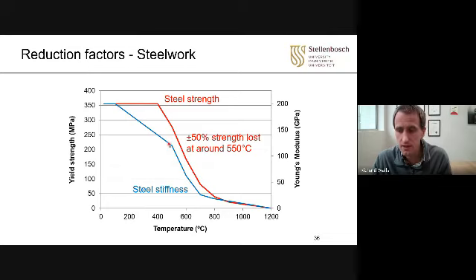So let's start thinking about steel and how steel is affected in fire. So this is the strength with temperature, the red line. As it heats up to about 400 degrees Celsius, the strength doesn't drop, more or less. And then at 400, it quickly plummets, all the way to 1200. By 1200 degrees Celsius, your steel has lost its strength. But normally at around 550 to 600 degrees Celsius, you've lost about 50% of your strength. So that's why you sometimes see these critical temperatures, 500, 550, 600. And it's roughly based on the load, the strength that you need is about half. So if you've lost half the strength, you're probably still fine.